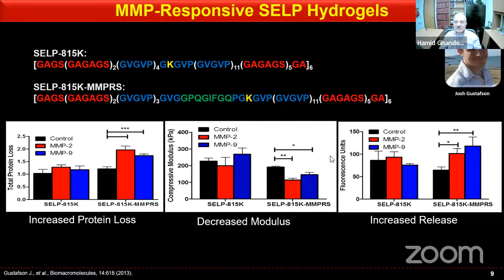One of the challenges that we had in those first generations, and I'm kind of fast forwarding, with the 815K, as you recall, was our lead polymer. And one of the challenges that we had, they didn't degrade fast enough in the tumor. Let's say if you want to deliver the material over a period of months, after a while, when we excised, we could easily excise the hydrogel from the tumor. And as a consequence, they were not degrading fast enough. So we were interested to design silk elastin block copolymers that would degrade in the tumor environment.